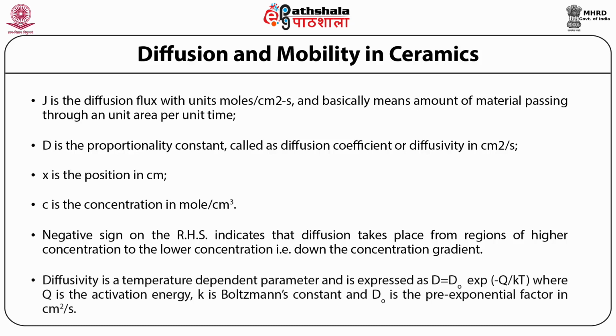The diffusivity is a temperature-dependent parameter and is expressed as D is equal to D naught exponential minus Q by KT, where Q is the activation energy, K is the Boltzmann constant, and D naught is the pre-exponential factor in centimeter square per second.